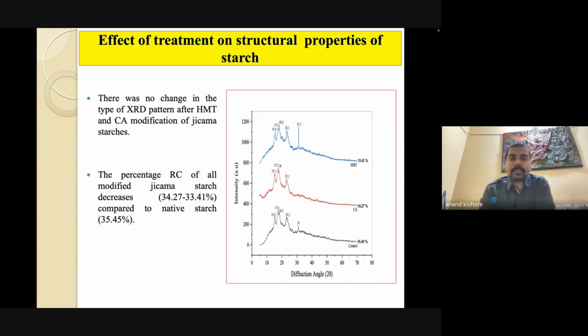We also did XRD patterns. We found no change in the pattern. We found the A pattern, with major peaks at 15.4, 17.2, 18.2, and 23.1. But there are some changes in the crystallinity. If we modify the starch, there is a decrease in crystallinity. The native starch has 35%, and the modified ones 34% and then 33%. With citric acid, the cross-linking may affect the crystallinity. In the case of HMT, the high heating treatment destroys the crystallinity, which may reduce the crystallinity of the HMT starch.